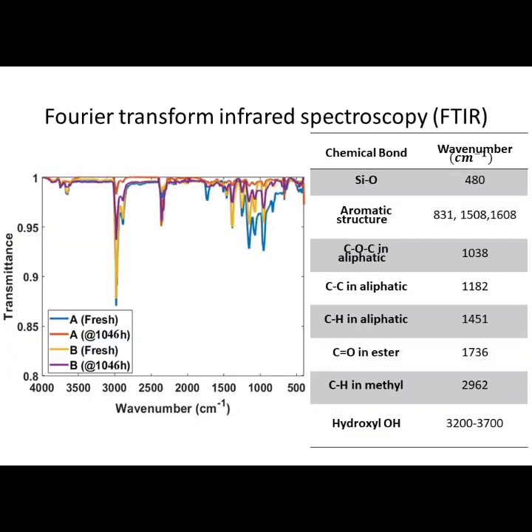FTIR analysis is conducted on both fresh and aged FRP rod samples to identify the molecular bonding over the sample surface and to determine the degradation level. This table shows the important chemical bonds in the FRP rod with the corresponding wave numbers. The transmittance peaks corresponding to the aromatic structure, methyl and aliphatic groups are found to be more in the fresh sample A compared with the fresh sample B, which indicates a higher content of the epoxy resin. This agrees with the TGA and also the EDS analysis before.